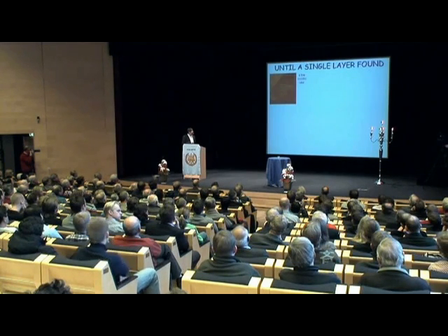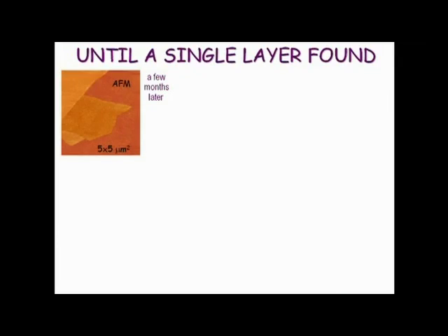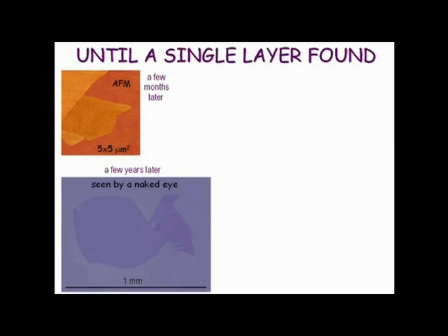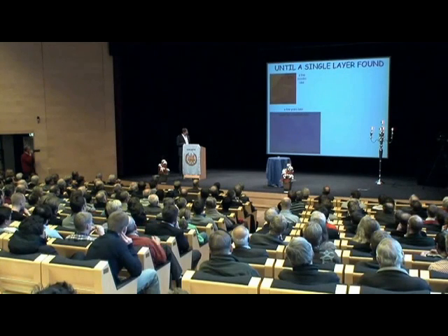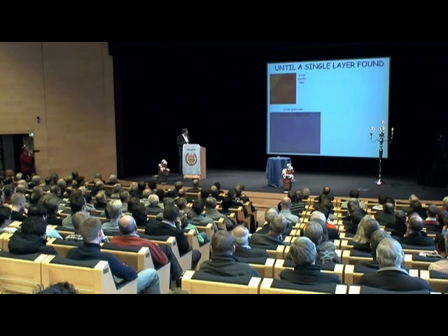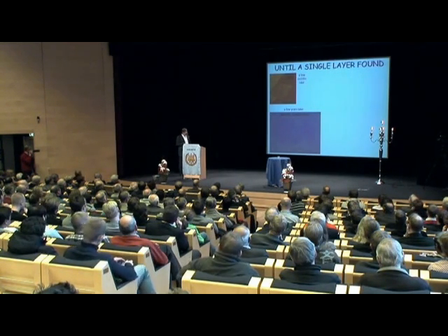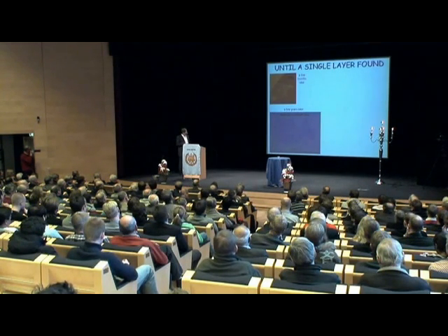Initially, it took a few months to go down to small pieces of single layers, and a couple of years later, we managed to get a single layer which is visible by naked eye. What you see here is a single crystal of graphene deposited on an oxidized silicon surface. Amazing that you can see it with your naked eye. Amazing that it's a single layer, and it's not big, but to make experiments, to make proof of concept devices, we don't need any more. You can make thousands of devices from one such piece, not industrial application, of course.